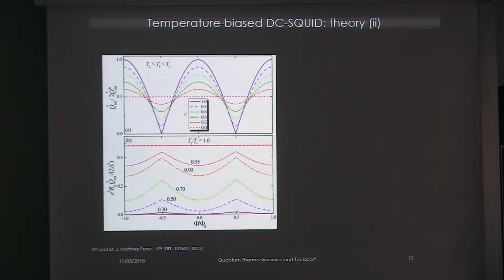So if we look at what is going on in terms of this interference part, being identical to the charge counterpart, by modulating the flux we obtain that the interference part oscillates as the absolute value of the cosine when there is ideality in the interferometer. So there is a maximum visibility, a maximum oscillation, whereas it tends to a smooth oscillation and then no oscillation at all by increasing the asymmetry of the system.